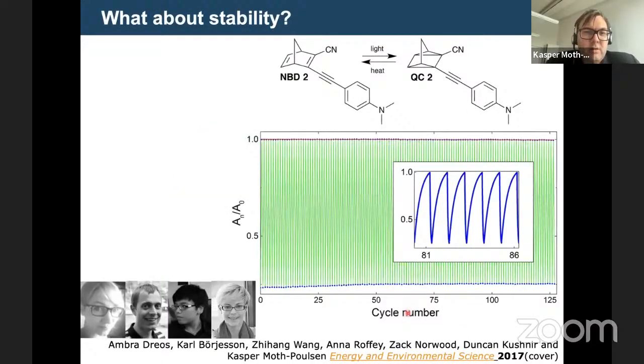You can also see that you can photo switch this for many cycles. Each point here represents one chemical reaction. So we start up here with norbornadiene, then we photo switch, then we make a quadricyclane, then we thermally react it back, then we make a photo reaction, and you can see here that we have almost full recovery. You see this slight slope here. So this is more than 99.9995% chemical yield per chemical reaction here. So it's a very efficient photo switch.